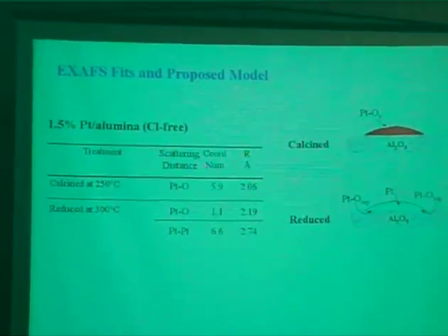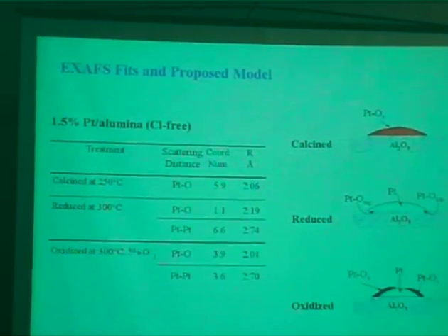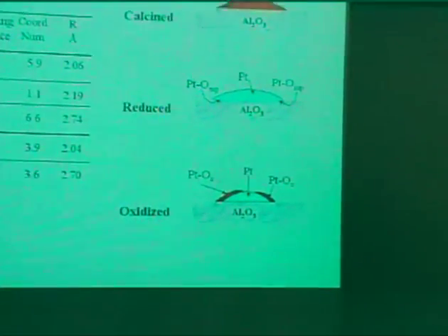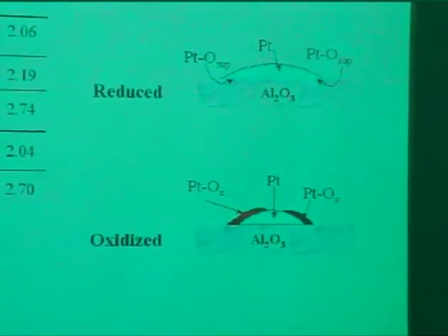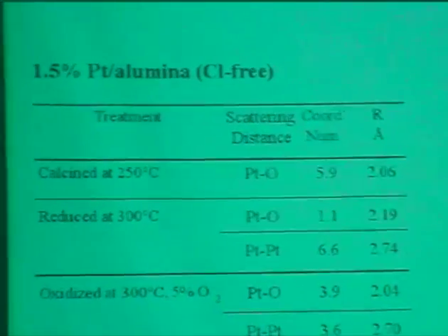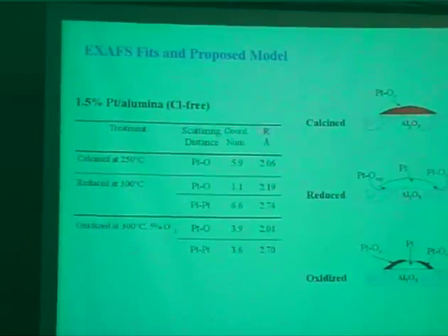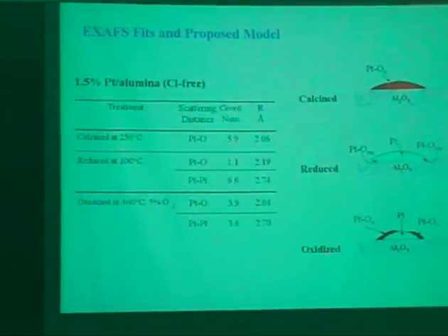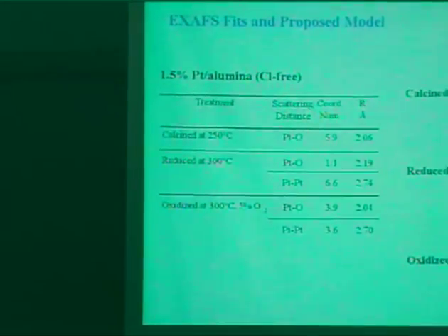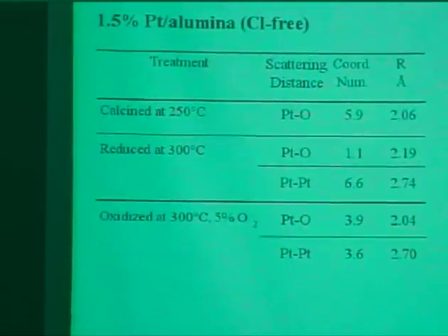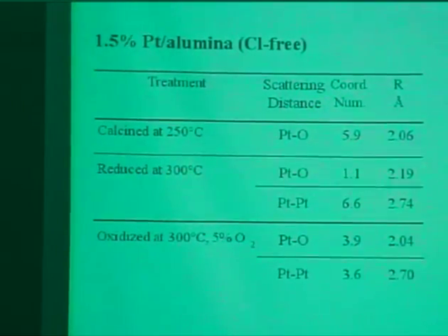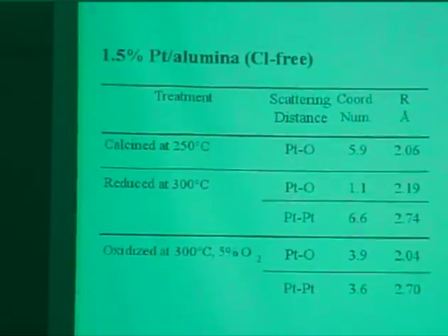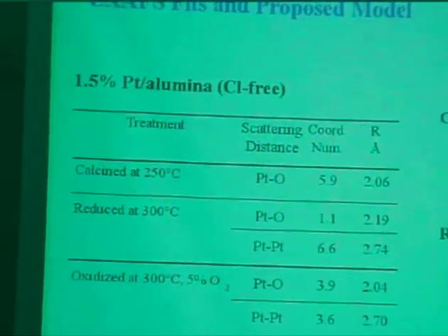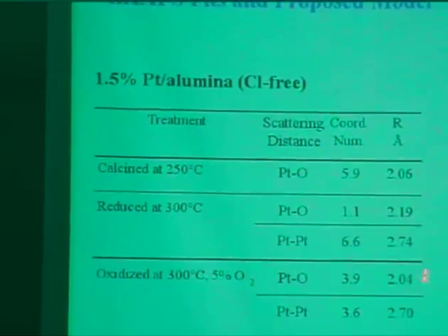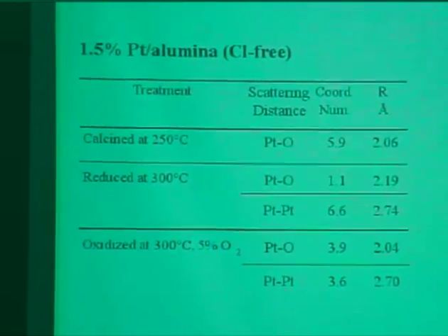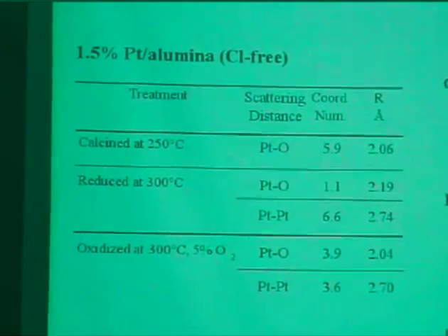So you can gain quite a bit of information by looking at the spectra. When we take the reduced catalyst and we oxidize, we recover some of the oxides. This is a function of time. Naturally, if you do it at a longer time, then you're going to see different coverage of the various species here. We see that these small particles are rather resistant to oxidation. So we see the platinum oxide as well as the platinum, 2.7 to about 210, I believe it is, the distance for the oxide.